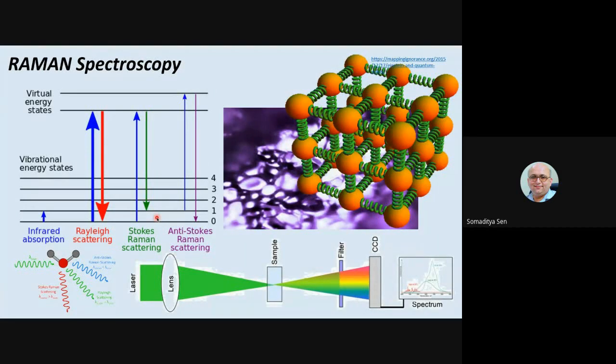Now, how does it help? If you have the model of the material, then that particular model of the lattice can support only a few vibrations that are possible in that configuration. The frequency of these will obviously change if you dope something, because it will involve a different mass. It will involve a different spring constant, that is the strength of the bond between the two atoms, right?